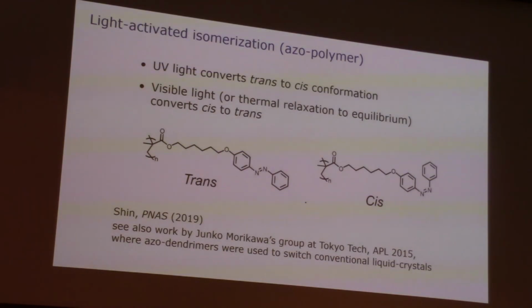So we had metals, and maybe more like electronic materials, maybe magnetics. Here's one from soft materials. Here's an example designed by the student, Jungwoo Shin, very impressive guy. He's doing a postdoc at MIT right now. He designed this whole system. It's a polymer with this side chain that has this azo group on it. When you shine UV light on it, this group transforms to a different isomer, which is no longer flat. So this flat system turns into this buckled system, and that changes how the chains are packed.